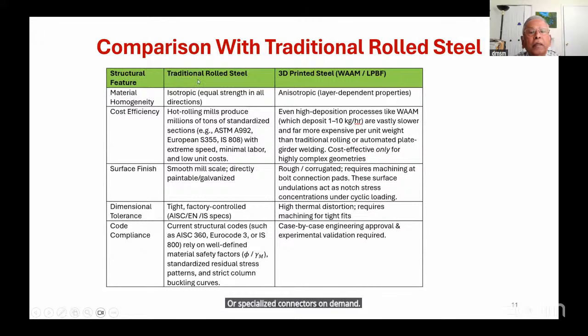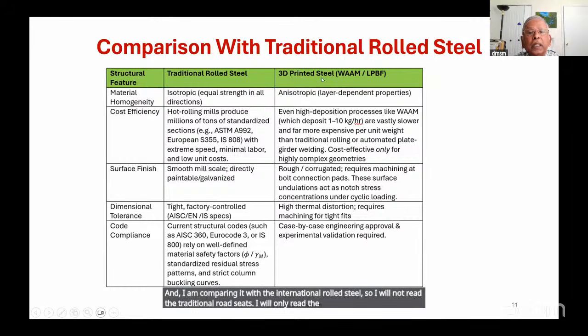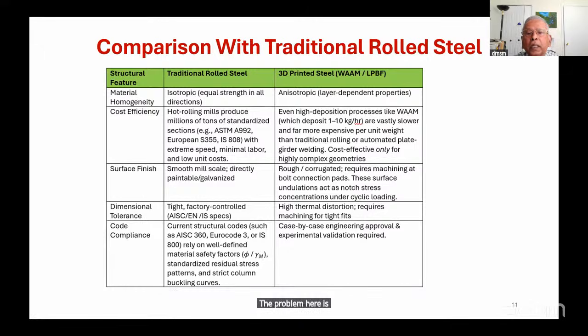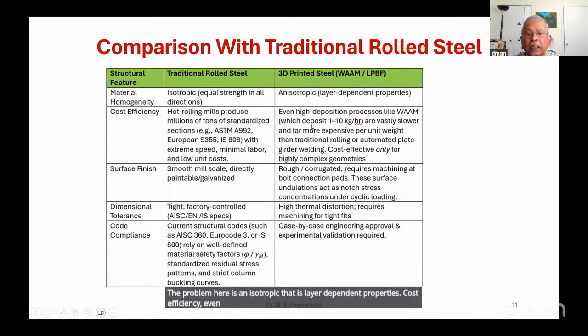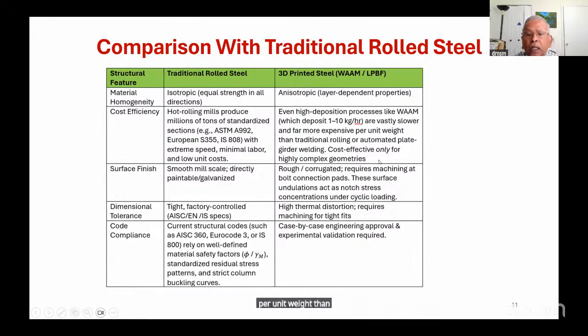And I am comparing it with the traditional rolled steel. So I will not read the traditional rolled steels. I will only read the 3D printed steel parts. So material homogeneity: traditional is, of course, isotropic, equal strength in all directions. But the problem here is anisotropic, that is, layer dependent properties. Cost efficiency: even high deposition rates, as I have shown, 1 to 10 kg per hour, are vastly slower and far more expensive per unit weight than traditional rolling. Cost effective only for highly complex geometries right now.